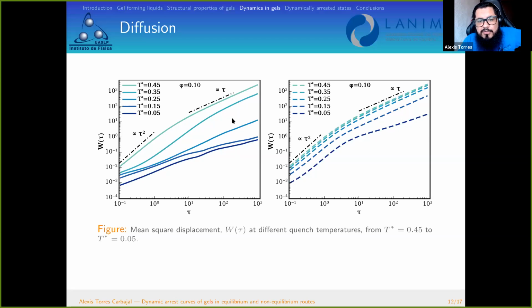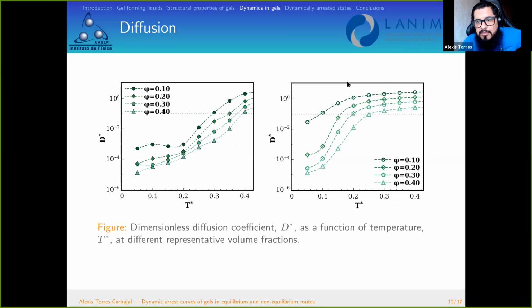This behavior is also seen for other densities; it is similar. So we determine the diffusion coefficient, and again, we see this dramatic change at certain temperatures, independently of the density, in the case of the Lennard-Jones fluid. But in the case of the Lennard-Jones fluids with Yukawa tail, we observe that this change of the diffusion coefficient takes place at different temperatures depending on the density of the system.